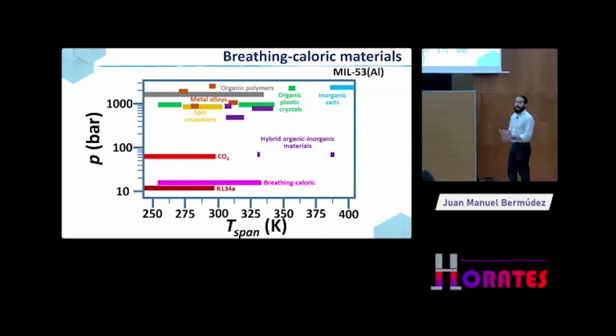And what is even more interesting is that we are using CO2 to pressurize the system. And remember that the CO2 could not operate above 31 Celsius. And in this way, we are able to use the CO2 beyond this critical point, so you can extend the use of CO2 for ambient applications, right, in warmer areas. So this is just a, let's say, fundamental study, a characterization of the thermal properties. So we have not used the material yet. We have not implemented the material in a prototype. So we will need to study the efficiency of this material in real working conditions, right? But so far, it looks quite promising.